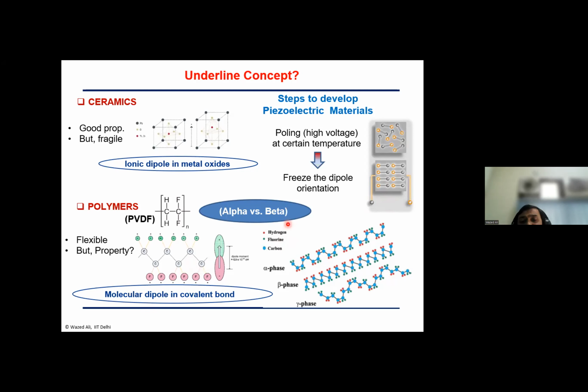So alpha versus beta structure of the polymer is very important. And this can happen in other polymers also, but I have taken this polymer because the carbon-fluorine dipole moment is very high, right? Because fluorine is the highest negative in the series, if you see. So alpha is non-piezoelectric, as I mentioned, because of the random orientation and fluorine on both sides. So the dipole moments are going to cancel each other, but beta structure is what is desirable for piezoelectric property.